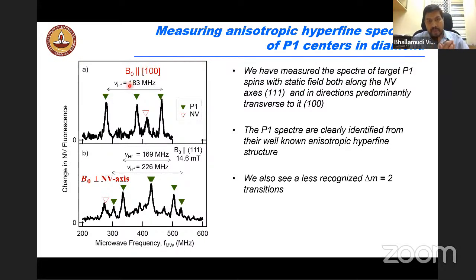And the advantage of doing something like this is that most of the NV techniques for doing magnetometry require you to have a field that is oriented along the NV axis, which is its quantization axis. So the coherent manipulation techniques require you to be oriented along the NV axis. But in this particular case, we don't need such constraints, and we can measure the anisotropic hyperfine spectrum of different paramagnetic species. And so that's one of the advantages of this technique.